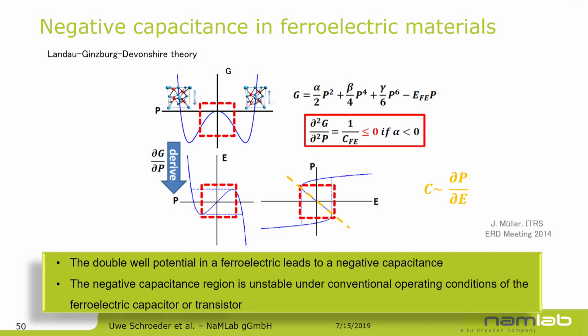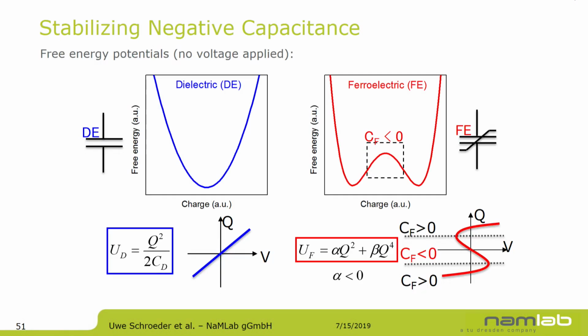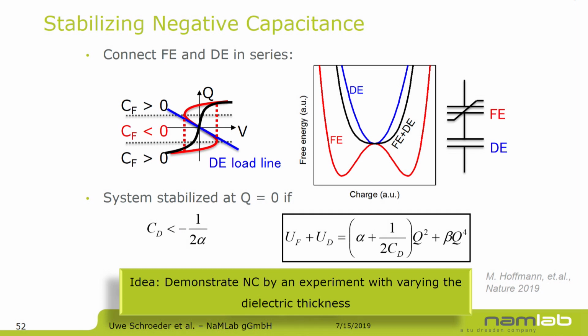And of course, you would go from a positive capacitance through a negative differential capacitance region, again, to a positive capacitance. If you typically measure your capacitor structure, you won't see this, because what you typically do is, from here to here, directly switch from one polarization orientation to the other. You wouldn't go through this whole S-shaped curve. The idea from Salahuddin and Datta at that time was, if you now combine a dielectric capacitor and a ferroelectric capacitor, adding the two, you would get to what they called a stabilized negative capacitance region for these two capacitors in series.